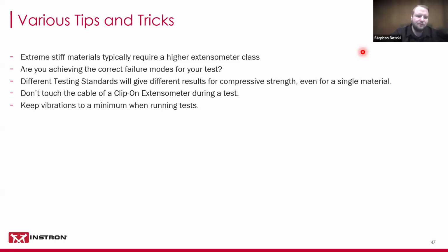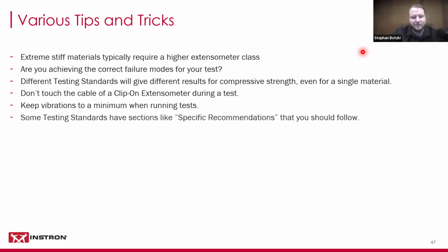Along those lines, make sure that you keep vibrations to a minimum when you're running tests, so not just on the test frame that you're using itself. For example, we've seen cases where there was a dynamic machine. I mean, lab space is always very critical, right? Everybody always wants to max out their lab space. So if you put a dynamic machine next to a static machine and then you're running a dynamic test, you might introduce vibrations during your static tests. And then obviously that data will be more likely to be inconsistent, or, if you're testing static and you don't have the dynamic machine running. So keep those things in mind.